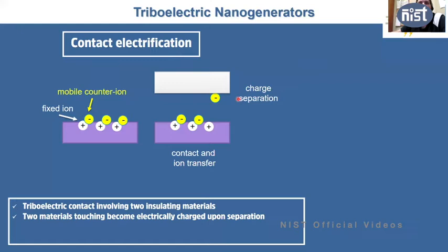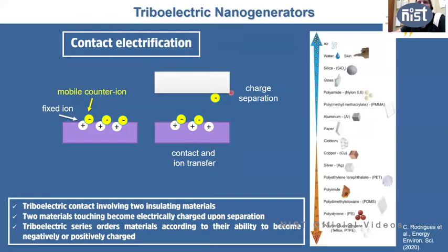So you get one negatively charged material and one positively charged material, and you can choose the materials from what is called the triboelectric series. This is known for over 100 or 200 years, and this series orders materials according to their ability to become negatively charged, so they capture electrons, or positively charged, meaning that they release electrons when in contact with another material. Typical materials you can find and use are nylon, which is very used when you make these devices, and PMMA. These are polymers, typically on this side. And on the other side, you get Teflon, which is very negatively charged, polystyrene, or PET.